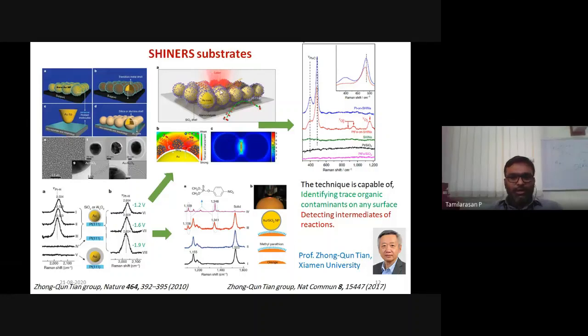Like, they observed the in situ chemical reaction using this substrate. What they have done is they took carbon monoxide, they oxidized it into carbon dioxide on a PtFe substrate. So what will happen if you oxidize it? Then you have to see the transformation from carbon monoxide to carbon dioxide. So just see this curve here on PtFe. People may have claimed that the SiO2 plays a major role here, because the SiO2 layer gives you an interference effect. Because of that interference effect, you will get slight enhancement in the Raman signal. But indeed, it is not true.